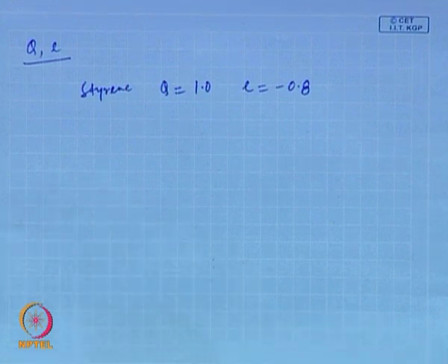And once you get the individual values for different monomers, those values of Q and E are further refined by copolymerizing monomers other than styrene. So, basically you first copolymerize with styrene, get the experimental values of R1 and R2, and from the expression you get Q and E for the unknown monomers, and then you refine these values of Q and E for the other monomers by making copolymers between them.